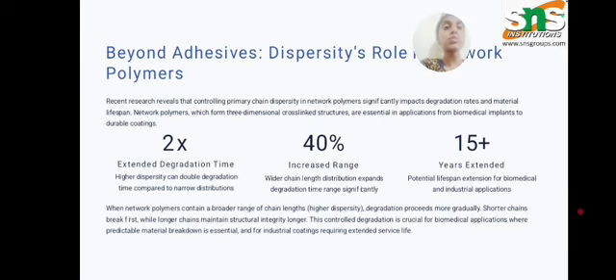Beyond adhesives: dispersity's role in network polymers. Recent research reveals that controlling primary chain dispersity in network polymers is essential in applications from biomedical implants to durable coatings. Higher dispersity extends degradation time. Higher dispersity can double degradation time compared to narrow distribution. A 40% increased range: wider chain length distribution expands the degradation time range significantly. It gives up to 15 years of extended potential lifespan for biomedical and industrial applications.